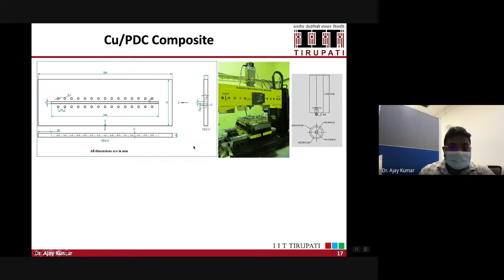So this was the idea that we will disperse the cross-linked polymer into the metal. This is the drawing of the sample. This is the 6 mm copper plate. We use copper as a matrix material and PDC as reinforcement. So we made the groove and the holes to insert the polymer particles according to the volume percent of the PDC materials. And then this is the 5-axis friction stir welding machine. This machine we used for making these composite materials.